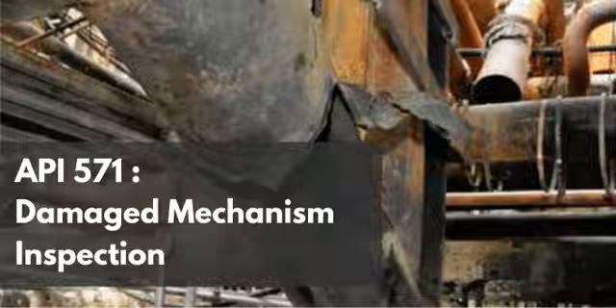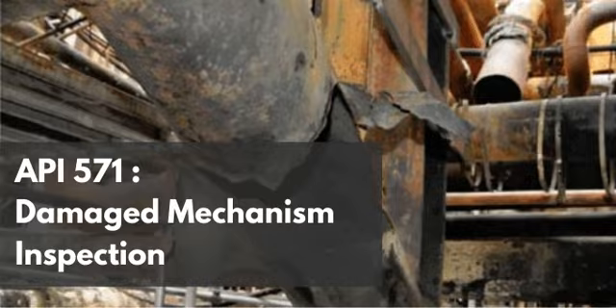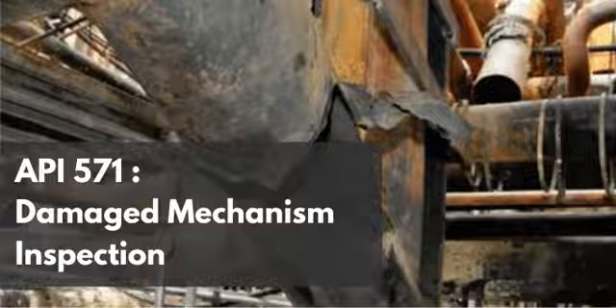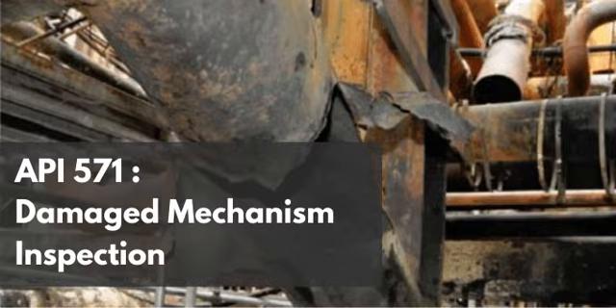It's all about the formation of a protective surface scale. Scale? Yeah. When the amine becomes rich with H2S, that hydrogen sulfide reacts with the carbon steel surface to form an iron sulfide, or FeS, layer. Now, in many other contexts, iron sulfide scaling is a huge problem. Oh, it's a nightmare in other units. Yeah. But in the specific context of amine SCC, that continuous, tightly adherent FeS layer actually acts as a barrier. It passivates the steel surface. Precisely. It physically blocks the amine from accessing and dissolving those highly stressed grain boundaries. The saturation of the fluid effectively seals off the initiation sites.